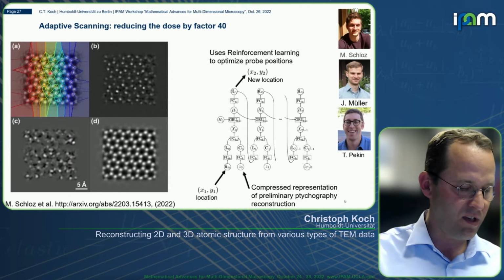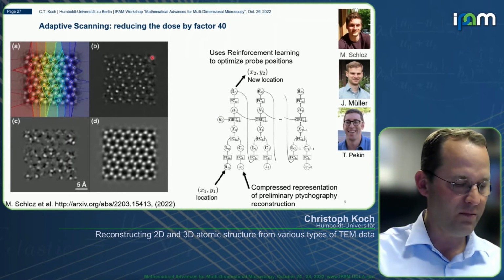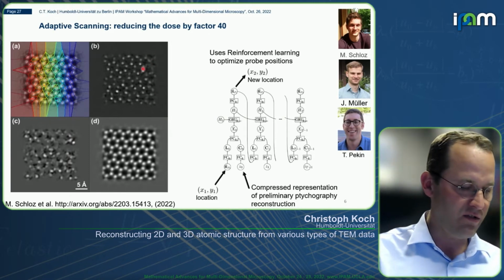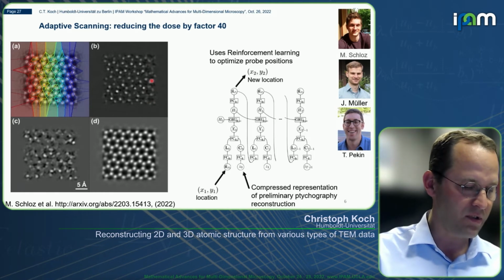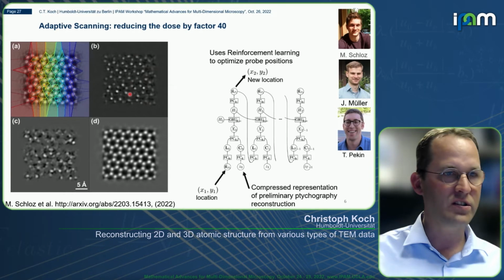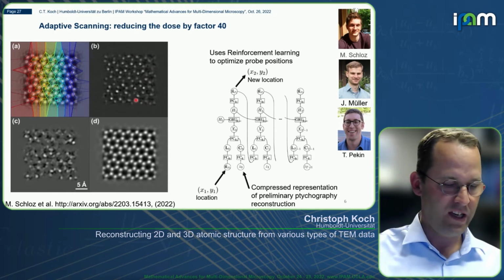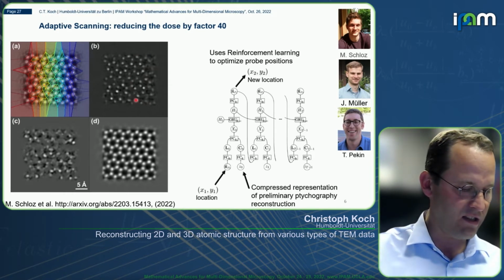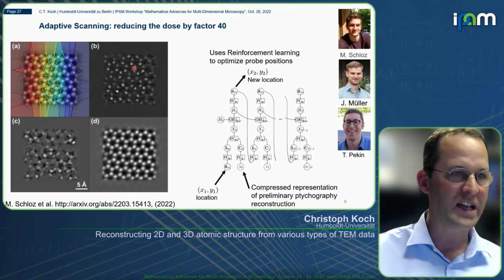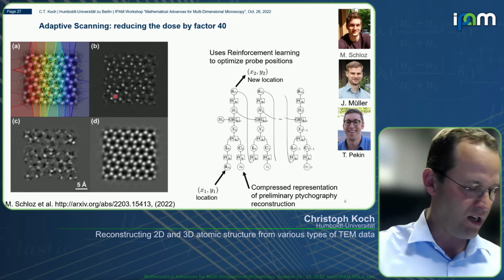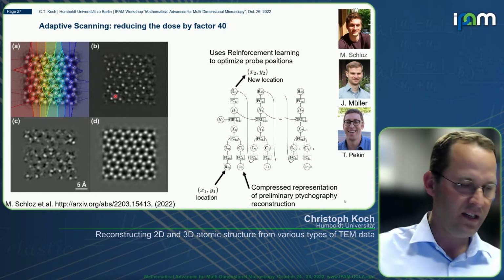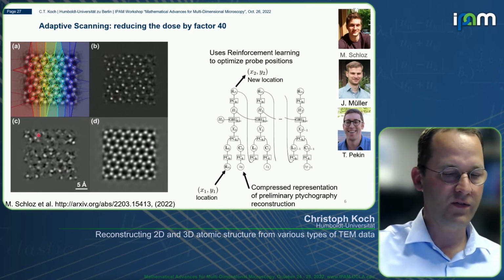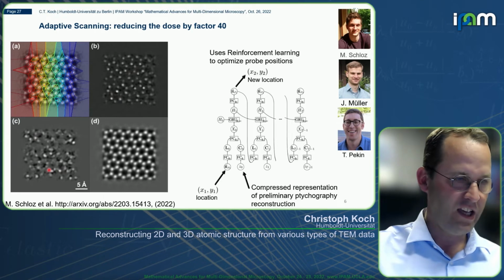And you can see here, the initial patch was reconstructed with random positions, but then using that information and the probe positions, the network was able to predict probe positions that led to a much improved reconstruction. And then at the end, you can see this is sort of consistent. At least all the atoms are being found, whereas if you just do a random scan, the reconstruction algorithm cannot find all the atom positions.